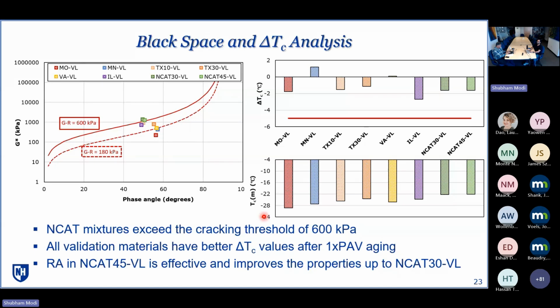Then coming to the binder testing side, we looked into the black space and delta Tc analysis that were identified from the core binder testing. And here we can see that both the NCAT mixtures are crossing the cracking limit of 600 kilopascal, and all validation materials have better delta Tc values after one-time PAV aging, and we can observe that the NCAT 30 and NCAT 45 mixtures.